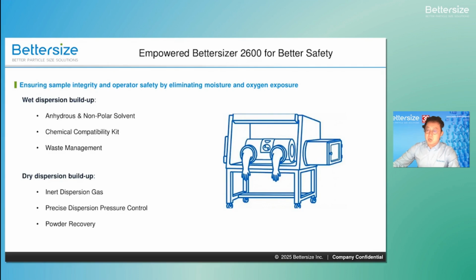As we just discussed, the beauty of the Bettersize 2600 is its modular design. It allows you to switch between wet and dry dispersion units on the same instrument. To apply this versatility to sulfide solid-state electrolyte materials, we integrate this entire system into a glove box. This gives you the flexibility to run wet dispersion with solvents or run dry dispersion with inert gas without even exposing your sample to the air.